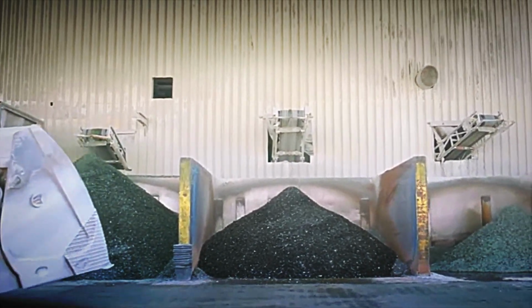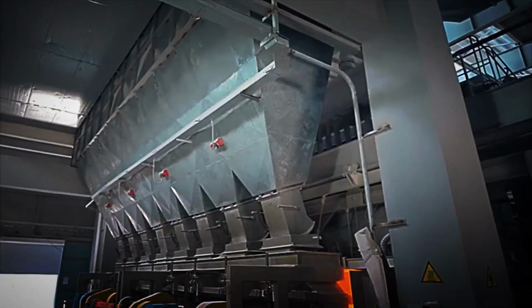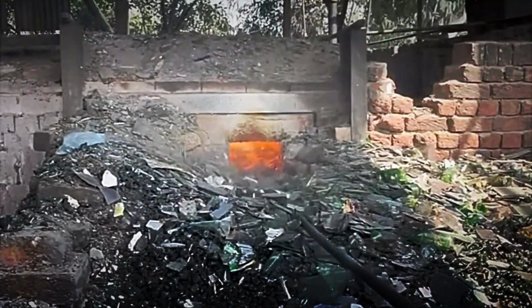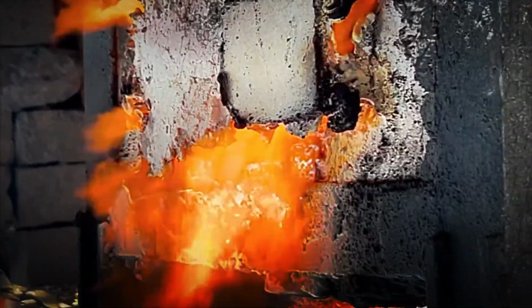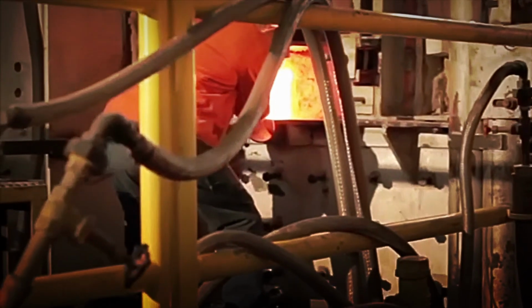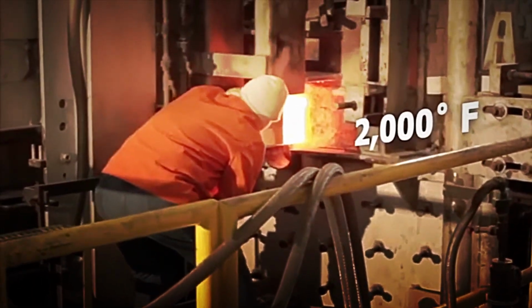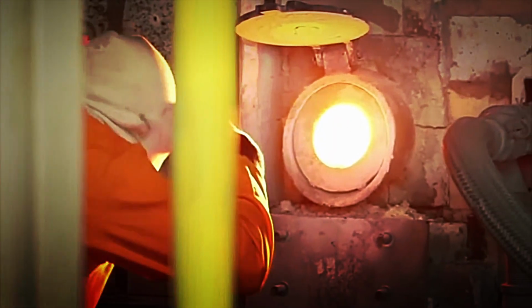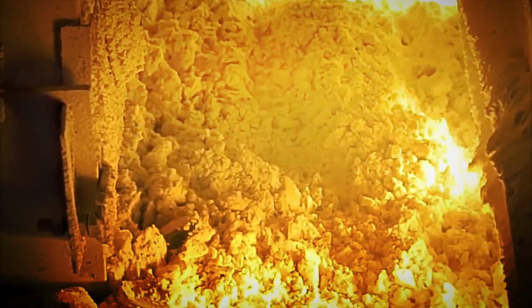The prepared mixture is continuously fed into large industrial furnaces that operate 24 hours a day. Each batch of glass is of considerable weight and is introduced at regular intervals. Inside the furnace, the temperature is maintained steadily around 1,100 degrees Celsius, comparable to the heat of volcanic lava. The environment is so extreme that workers must wear fireproof suits and special gloves to protect themselves from the radiant heat. Inside the furnace, solid particles gradually soften, merge together, and turn into a completely liquid state. The molten glass remains stable for hours, allowing trapped gases to escape and the composition to become homogeneous. Specialized technicians continuously monitor the temperature and flow, ensuring that the amount of glass entering the furnace is perfectly balanced with the amount exiting from the bottom.